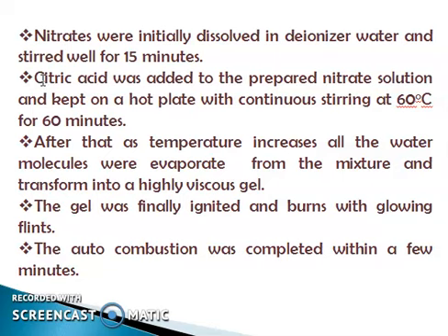Citric acid was added to this nitrate solution, and this complete solution is kept on a continuous magnetic stirrer, and we heat this solution at 60 degrees continuously for 1 hour.